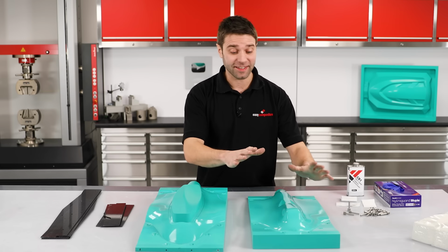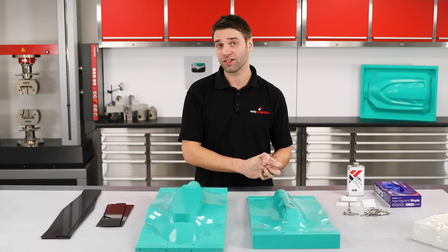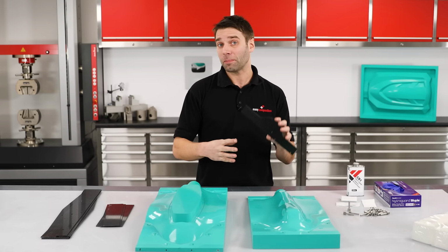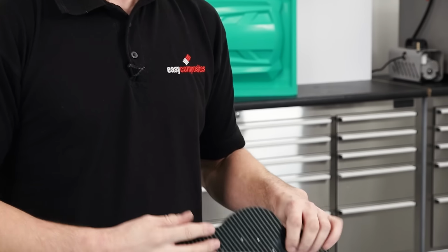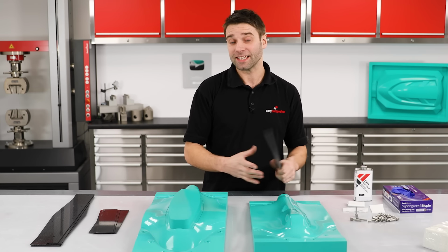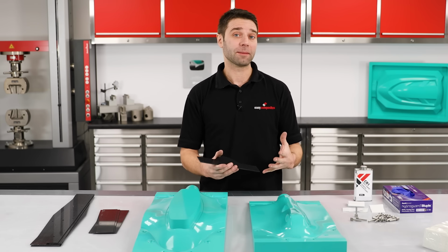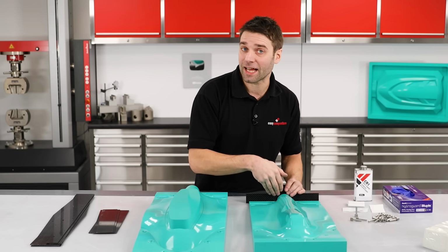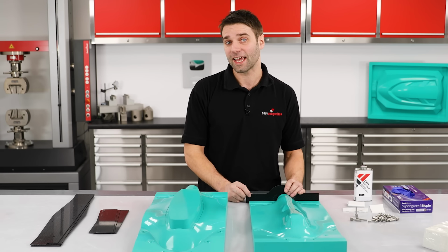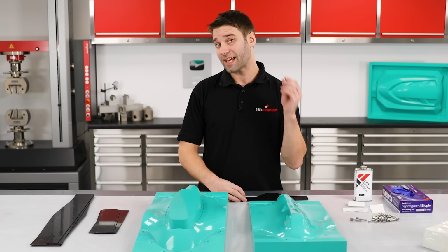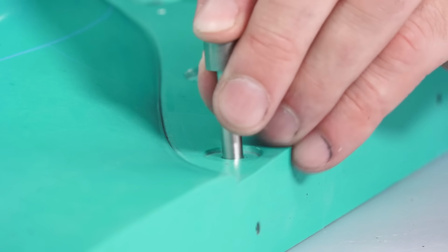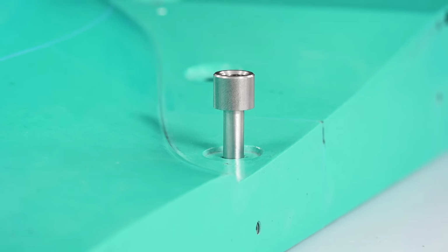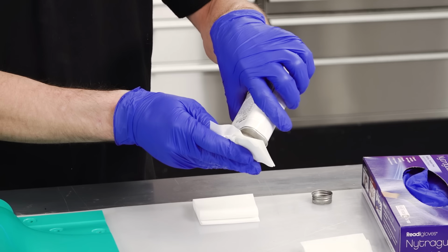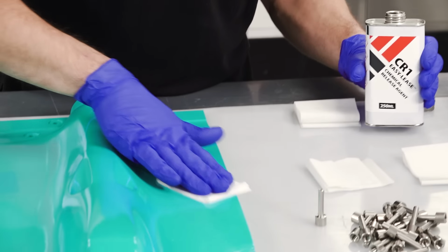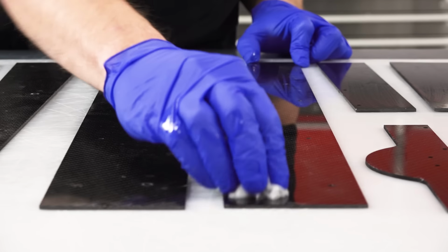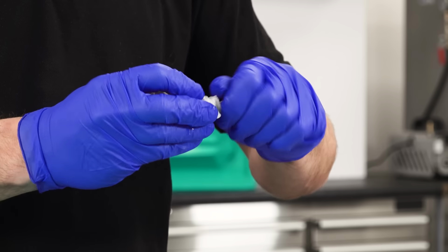As ever, before we get into the lamination, we're going to need to apply a release agent onto the patterns. We're also going to need to apply release agent onto this shuttering as well. Whenever you have a multi-piece assembly like this, it's best to put the release agent on before you assemble it. That way, any resin that does bleed down between the gaps won't bond the pieces together. We're also going to be coating the dowel pins. Now, these are the extractable pins that are used to locate the clamping bushes onto the pattern. So I'll be applying 6 coats of CR1 chemical release agent to the patterns, the shuttering, and the pins.